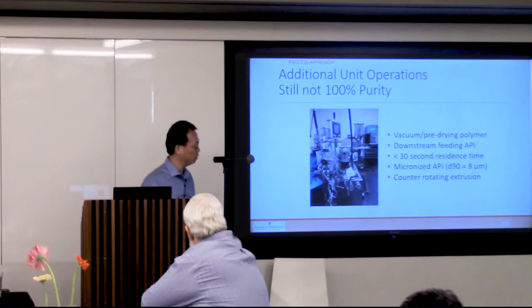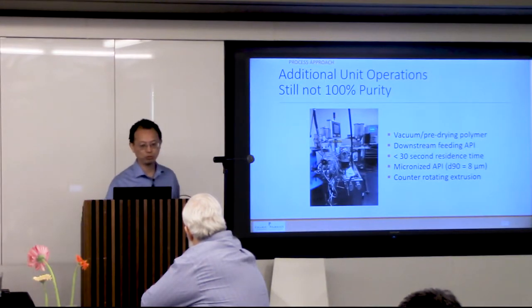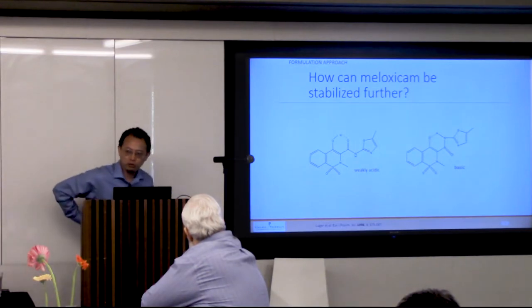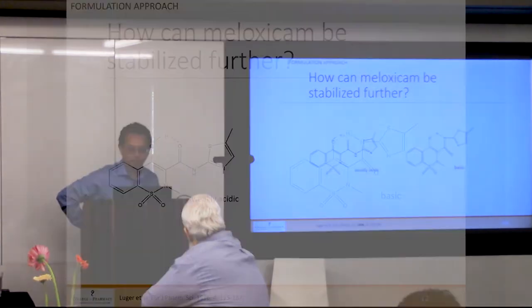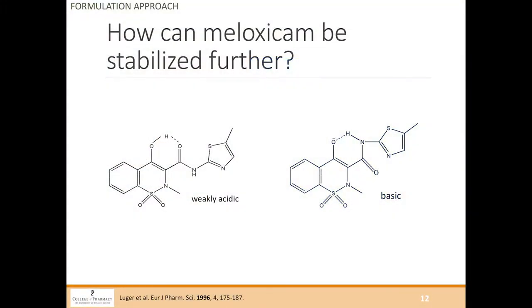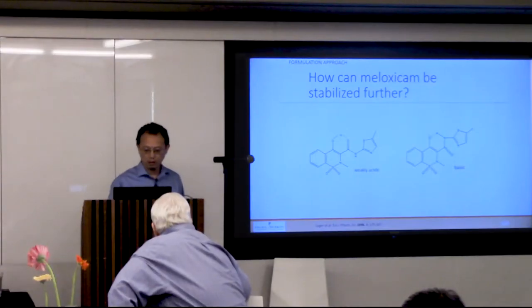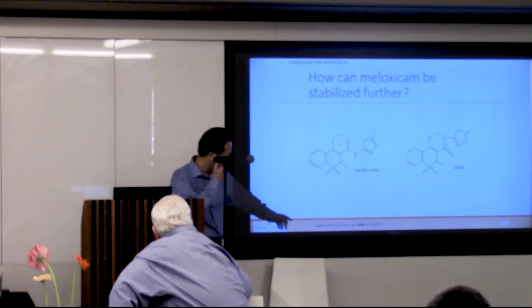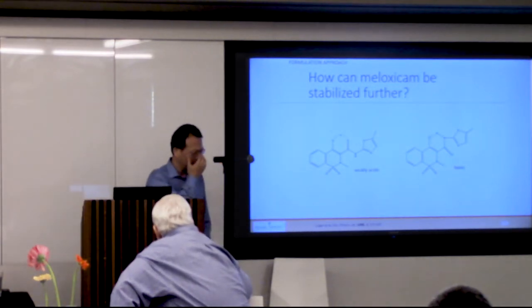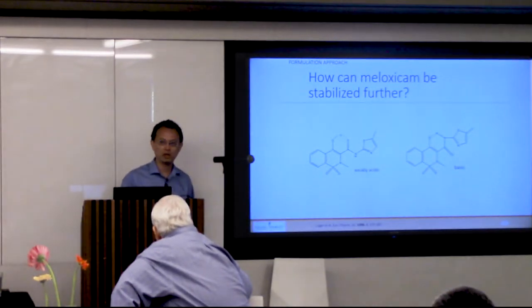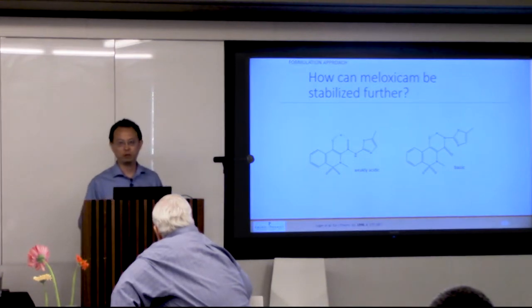But with all that, we even tried the counter-rotating in twin-screw extruders. We still couldn't get rid of all the impurities. The best we can do is about 2% degradation. Then we start looking at this, what can we do from a chemistry perspective? Well, we found an article back in 1996. Meloxicam actually does not degrade very quickly at high pH.